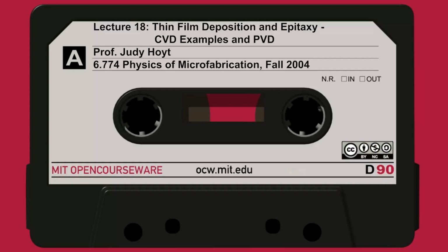As the grains grow, there's a certain amount of induced surface roughness, so that the surface is much rougher than it was in the as-deposited case. It's typical, of course, to anneal a polysilicon film during the source drain annealing or whatever to activate dopants. So this is more like what it might look like in a gate material.